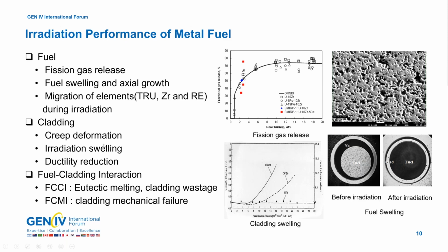For cladding, there is always the tensile stress. So because of that, the cladding creeps out, and also with the high fast neutron flux, the irradiation swelling occurs on the cladding, and because of these two behaviors, cladding ductility is also reduced. This shows the cladding swelling. This is the HT9 data. HT9 has the body-centered cubic lattice structure, so it shows the lower swelling rate. And this one is the austenitic cladding, face-centered cubic. It's more closely packed, and it has a higher swelling rate.